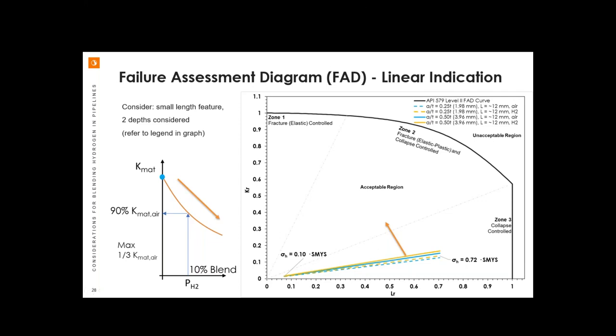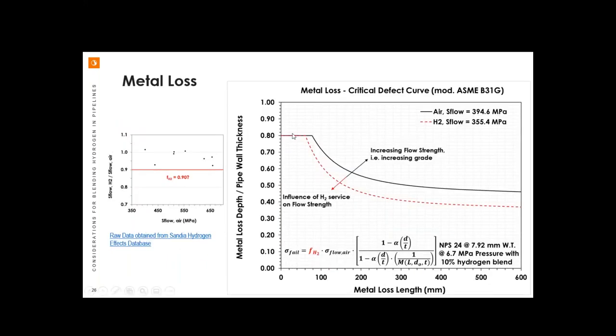Okay, I have 4 crack scenarios, and I just want to go back to the metal loss here. Envision this as a critical crack curve instead of a metal loss defect curve. The 4 scenarios that we're going to look at is small depth, small length features, and then we'll increase the depth a little bit on one of the features, and then we have 2 other features that are a little bit longer. So we're kind of well within an acceptable size for initial starting features.